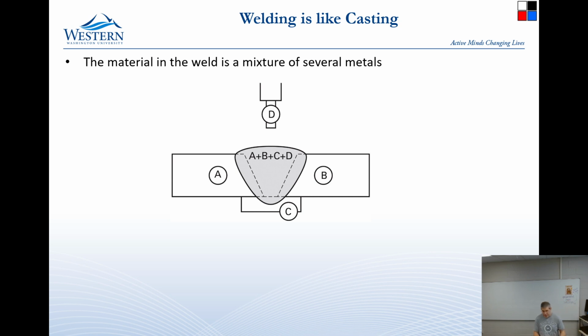We can match a weld where we put in the same strength material as the base materials, but the problem is, because this is uncontrolled cooling, even though it was the same strength when it went in, it isn't anymore. Because it cooled at some random rate.